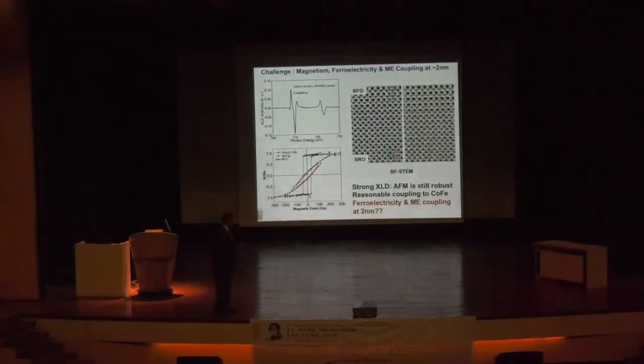So we don't know if a 2 nanometer layer is ferroelectric or simply has broken inversion symmetry. And so we're now getting into trying to understand how does one switch a 2 nanometer thick layer of these kinds of materials, which is where we need to be to reduce the voltages significantly. Okay. What we also know is that there is strong linear dichroism, which means it's still antiferromagnetic. We know that for sure. We know that it couples to a ferromagnet reasonably well. What we don't know is how do these magnetoelectric coupling work at these kinds of dimensions.